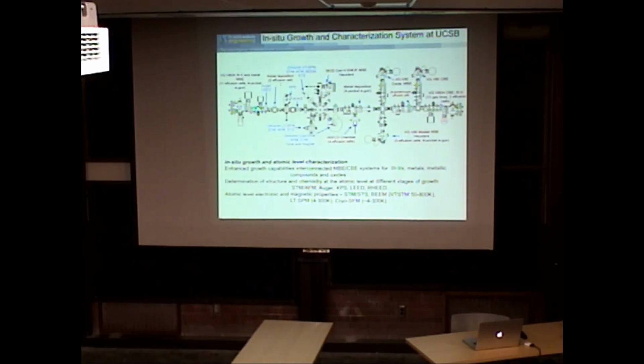So just as I go down it, here we have low energy electron diffraction and Auger electron spectroscopy. We have some metal deposition here. We have X-ray photoelectron spectroscopy we can do here. We can do magneto-optic Kerr effect in situ for looking at magnetic materials. Coming down here, we've actually got 3 scanning probes attached to the system, a low temperature one, a variable temperature one, and one which will drop into a vector magnet.